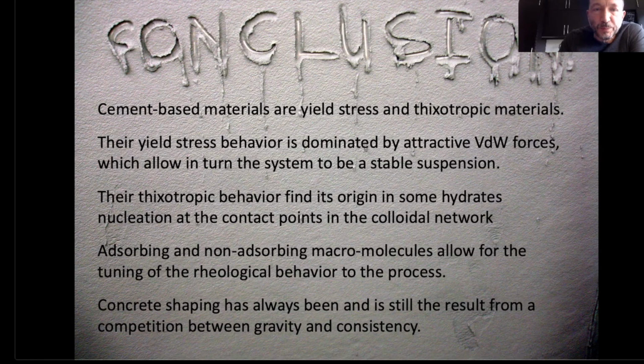So all in all, cement-based materials are yield stress and thixotropic materials. They build up a structure with time, either due to flocculation or to nucleation of hydrates. Their yield stress behavior is dominated by attractive van der Waals forces, which prevent the material from being extremely fluid, but allow the material to be stable. The thixotropic behavior finds its origin in some hydrate nucleation at the contact points in the colloidal network, and adsorbing and non-adsorbing macromolecules allow for the tuning of the rheological behavior to the process, but that is something that I have not talked about here today, but that is one of the books that I suggested in the introduction.